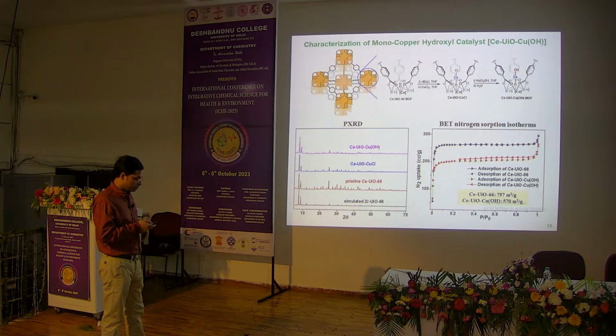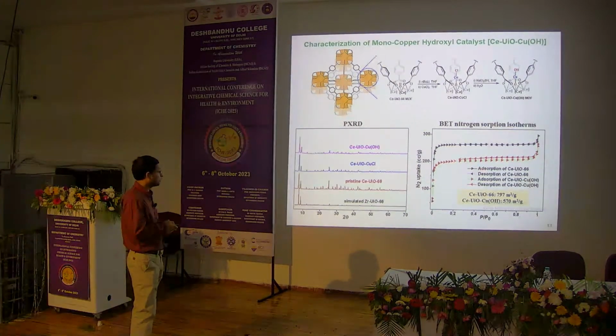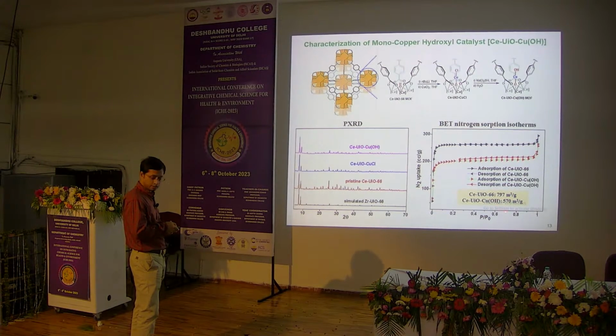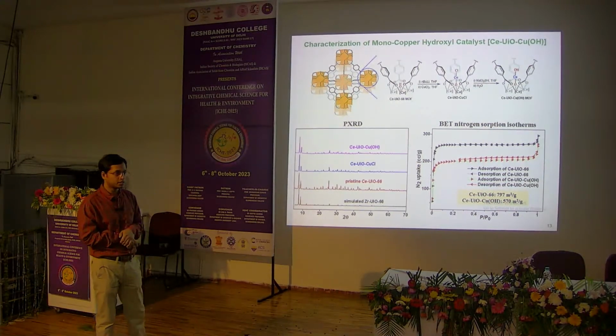The MOF catalyst also has a high surface area. It is highly porous. Before metallation, it has around 800 square meters per gram, and after metallation, because of the incorporation of the copper hydroxyl groups, the surface area decreased as expected to 570 square meters per gram.